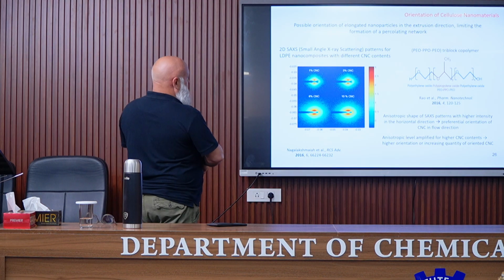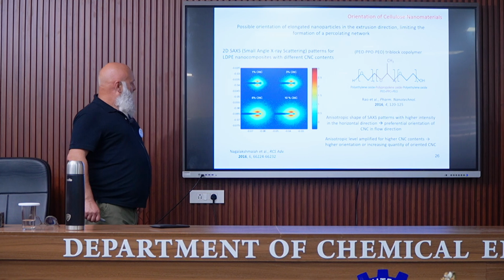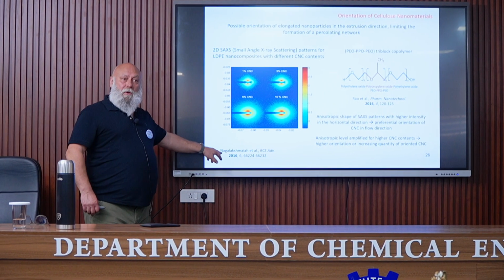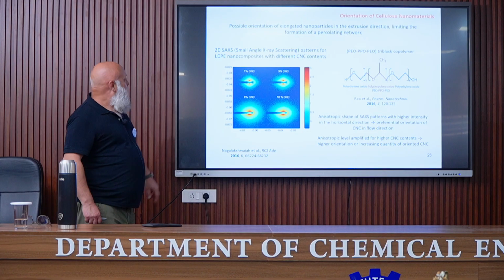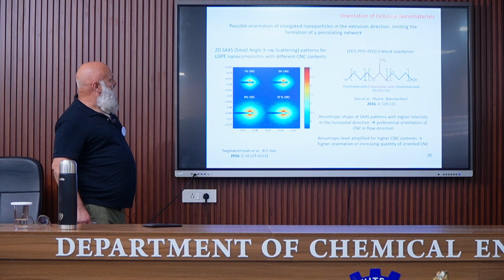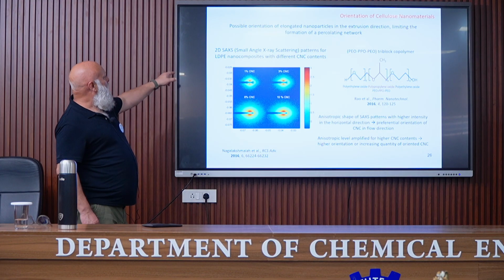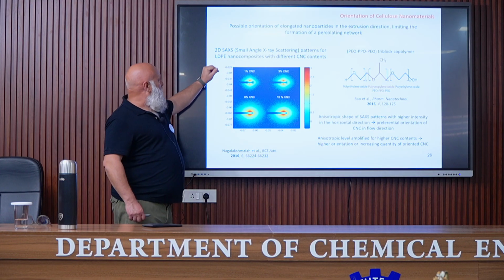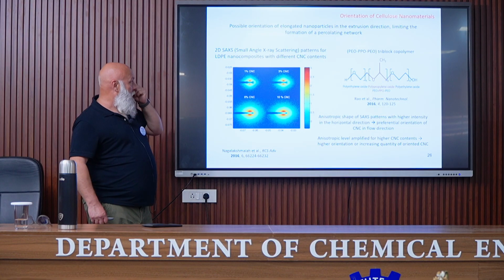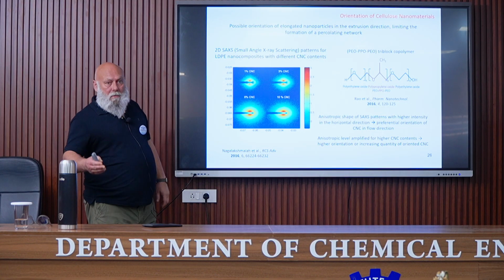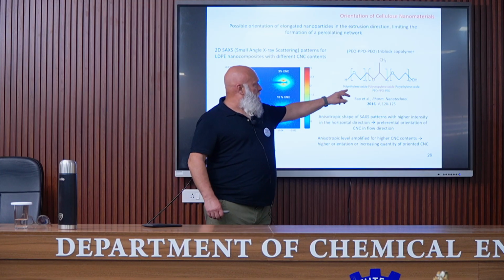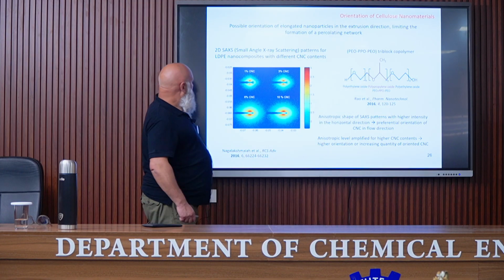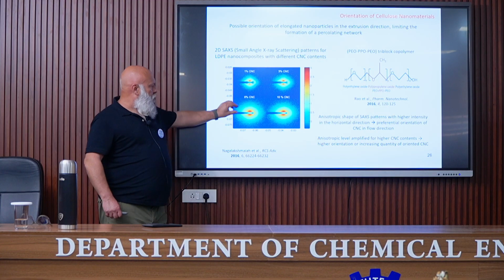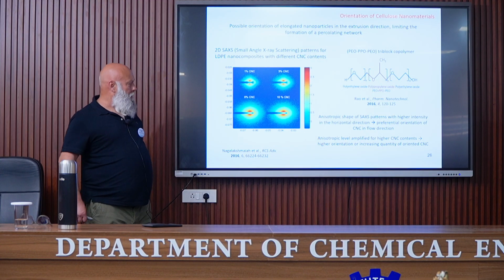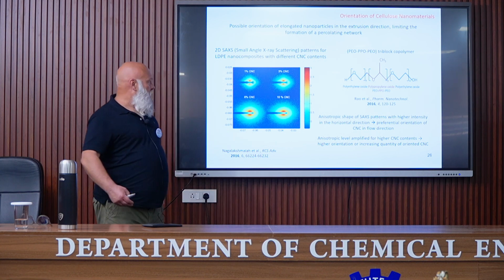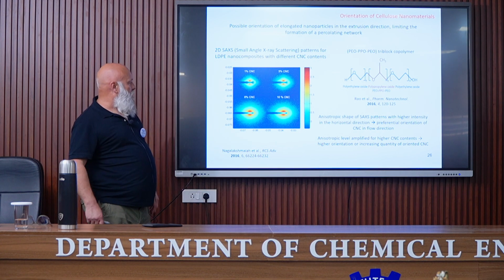To observe this orientation, this was a PhD from Kerala, we used small angle X-ray scattering for a nanocomposite consisting of low density polyethylene and cellulose nanocrystals. They were compatibilized using this triblock copolymer. And what we can observe is an anisotropic pattern of the signal, which is an indication of some orientation of the nanocrystals.